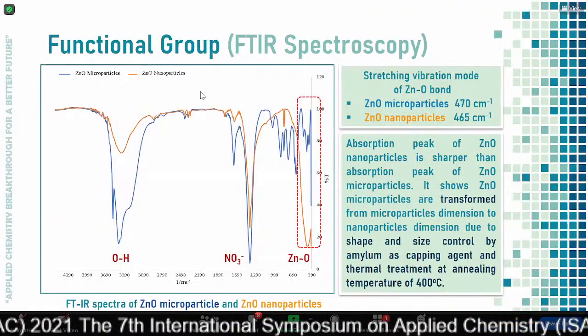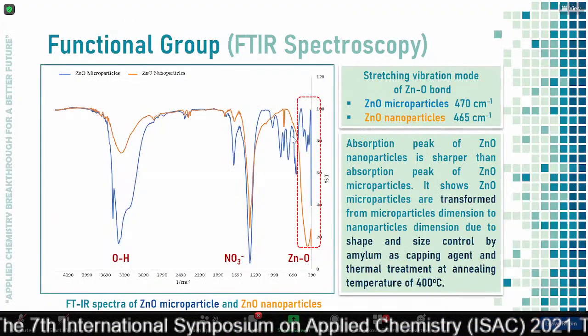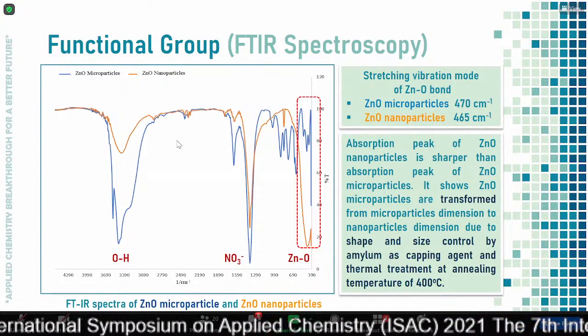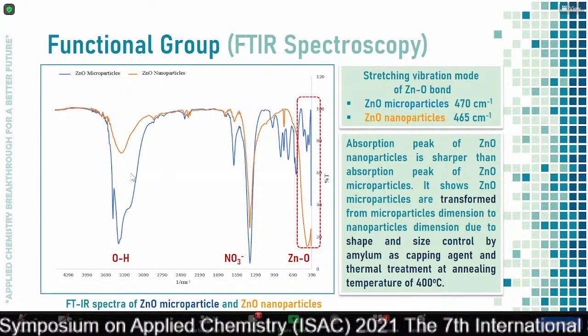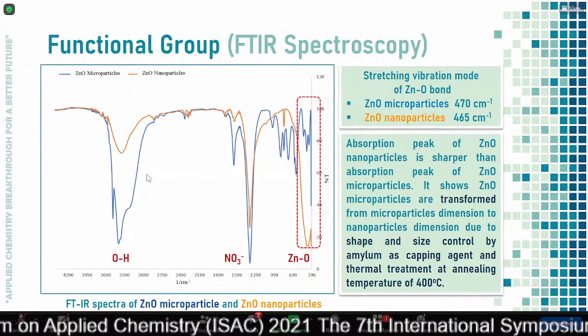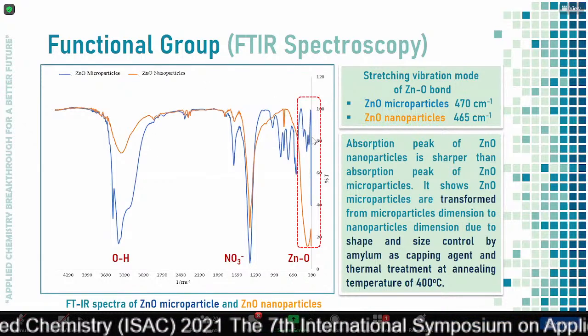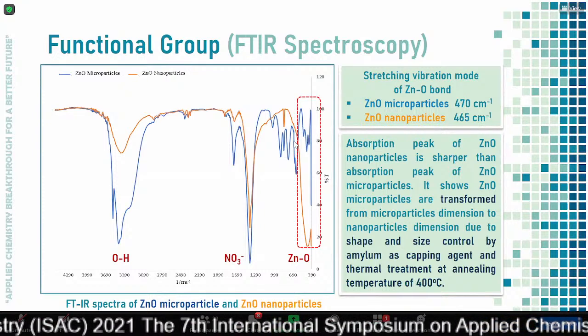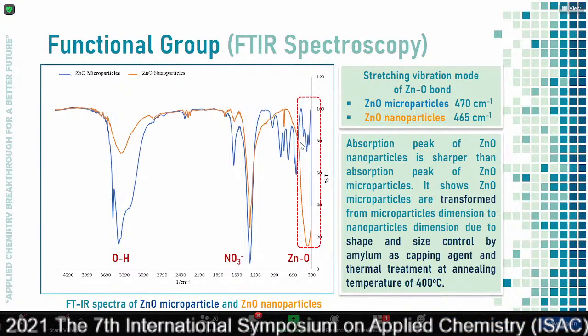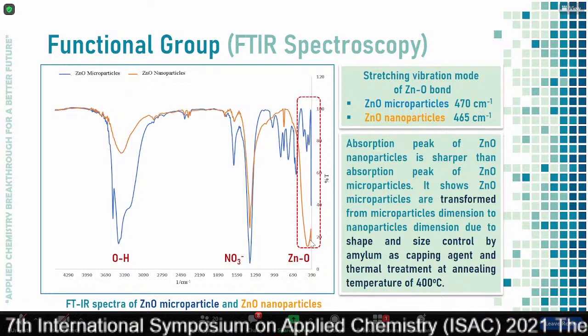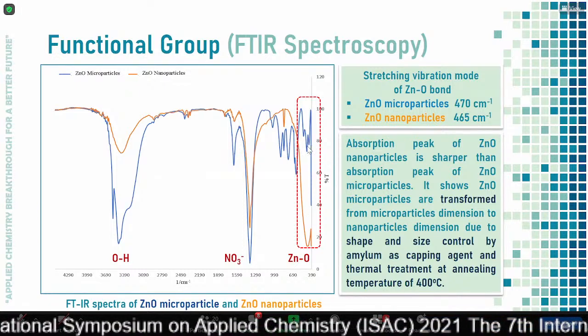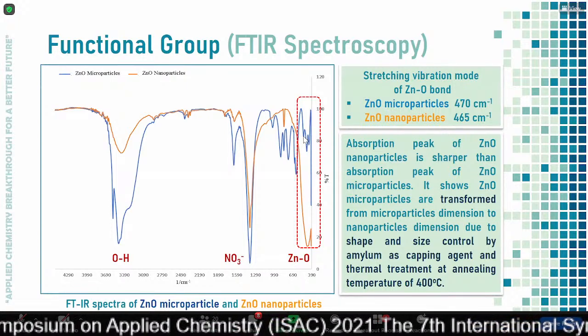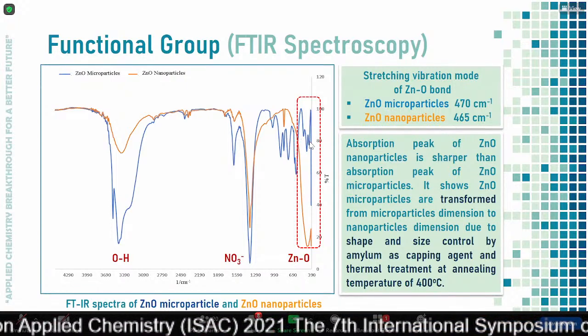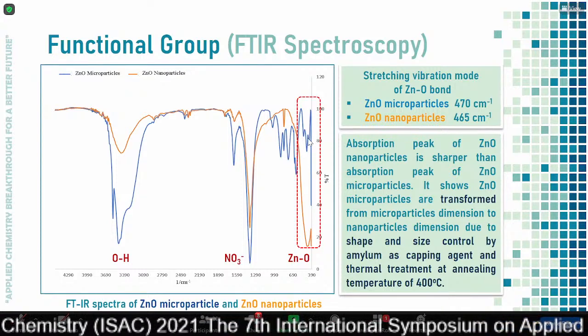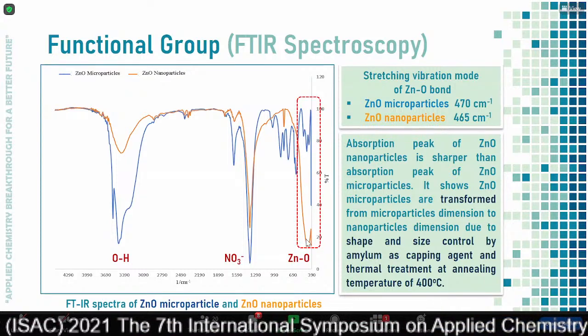If you look at this one, the blue one is zinc hydroxide. This is basically still zinc hydroxide. It's only a small quantity of the composition of zinc oxide microparticles, as compared with the zinc oxide nanoparticle here. This is confirmed by the zinc-oxygen stretching vibration in the microparticle, and this one in the zinc oxide nanoparticle.